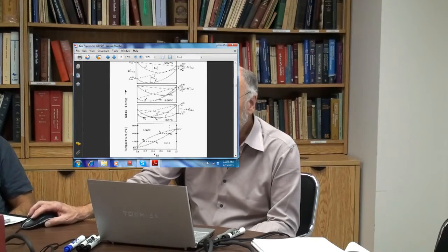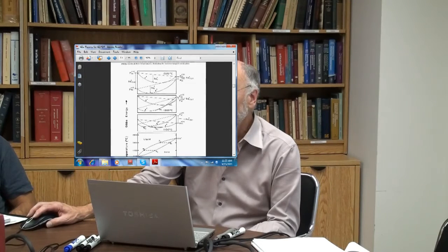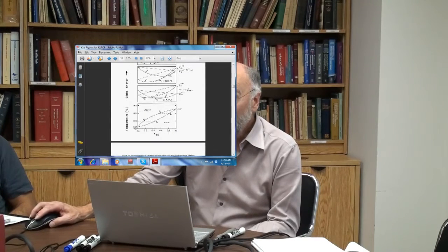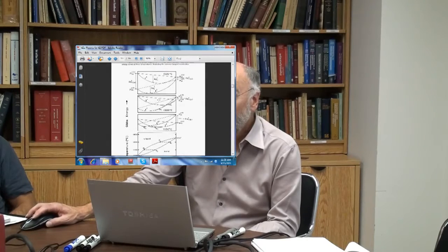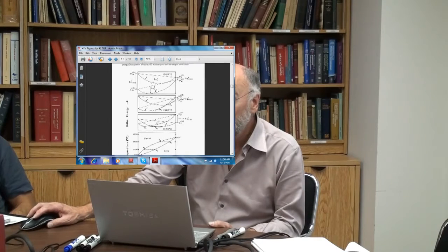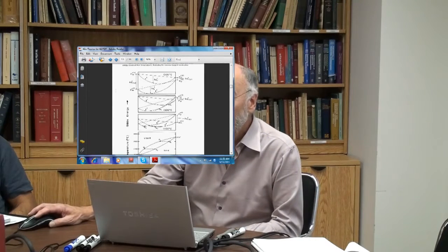Okay. This is at 1500 degrees, which is up here, completely in the liquid range, where the pure liquids are more stable than the pure solids. So everywhere, including the two ends, the liquid phase is more stable than the solid phase, more negative Gibbs energy. Okay, so the liquid's always stable. Suppose we now lower the temperature. If we lower the temperature, several things change. The Gibbs energies of mixing will depend upon temperature. But to a first approximation, let's assume that the Gibbs energies of mixing don't change that much with temperature. What really changes is the Gibbs energies of fusion.